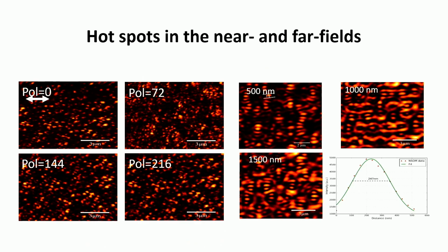Right. So I mentioned the near-field properties which are interesting, and the dense K-space. One of the applications is that if you look at the near field, even up to 1500 nanometers above the surface, you see that there is a very dense distribution of hotspots on top of this surface. So these are interesting for sensing applications. So this is what we showed.